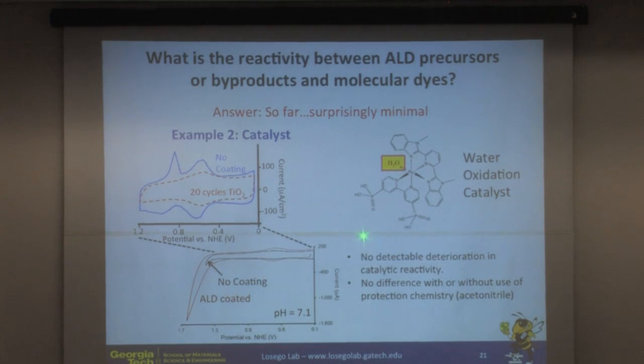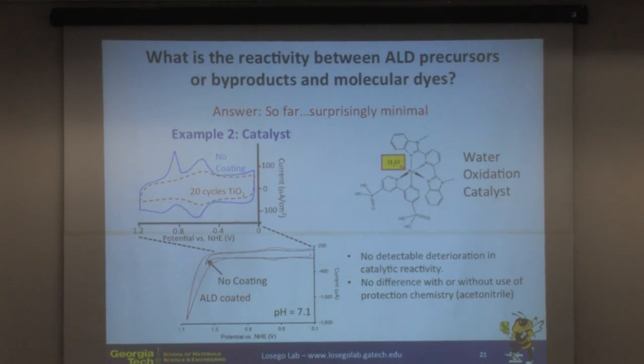We've also looked at this catalytic molecule that's used for water oxidation. We thought for sure that this one would react. We have an actual aqua ligand here on the ruthenium site, and many of our ALD precursors react with water. That's the co-reactant. So we actually went through a whole protection chemistry on one of the first experiments we did. It turns out that using protection chemistry or not using protection chemistry, we got the same results. The material was still catalytically active.